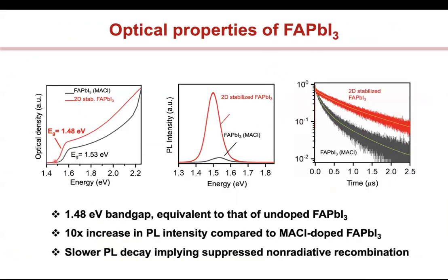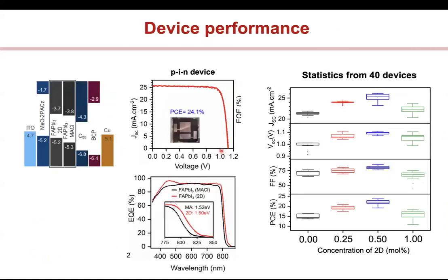The band gap is 1.48. This is the lowest reported for a lead-based perovskite. And you get very nice long lifetimes of microseconds. And these are very, very stable films. Okay. And you get nice devices and chips. These are about half a centimeter square, 24% efficiencies, a lot of very nice statistics.